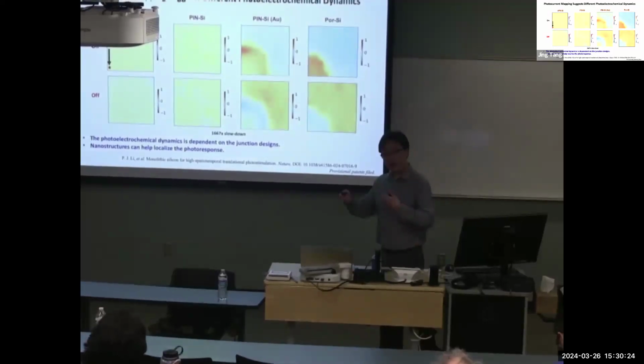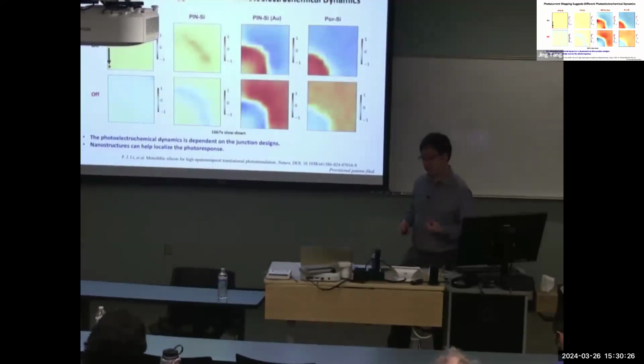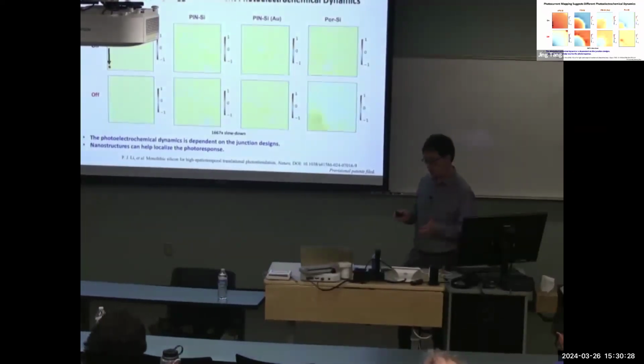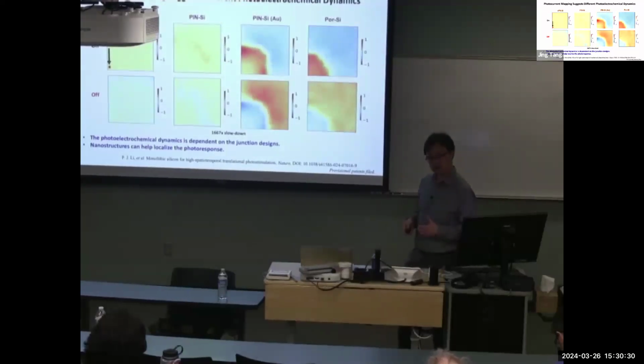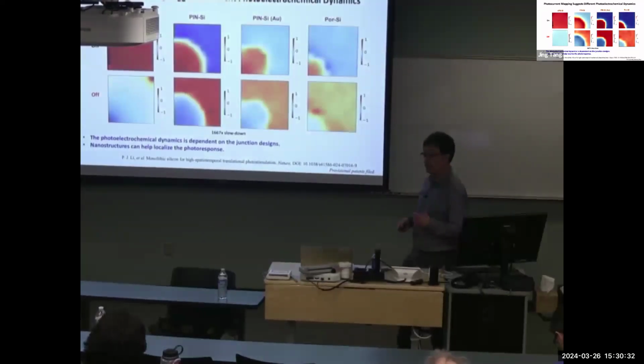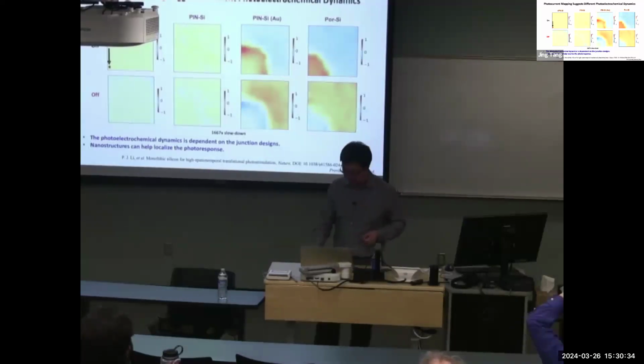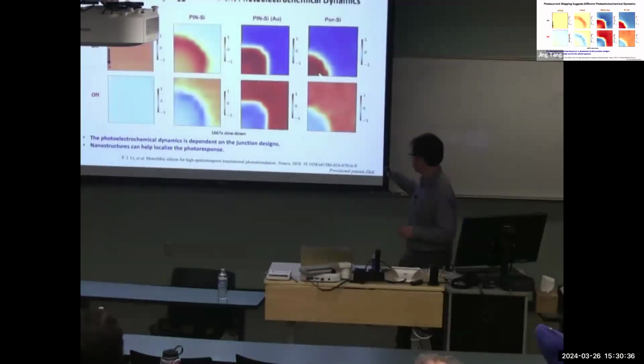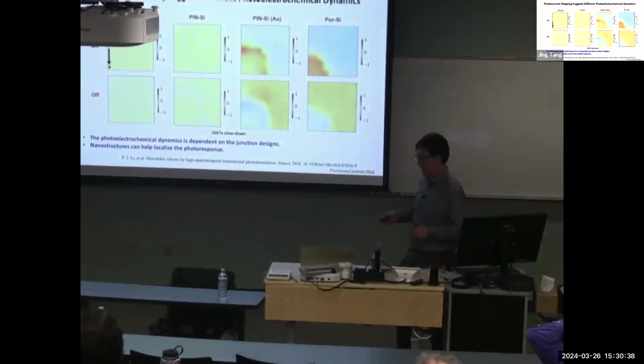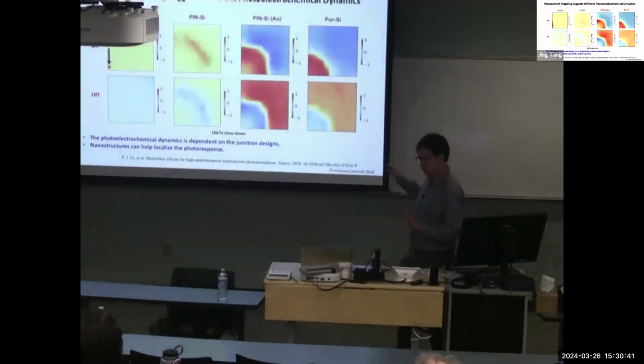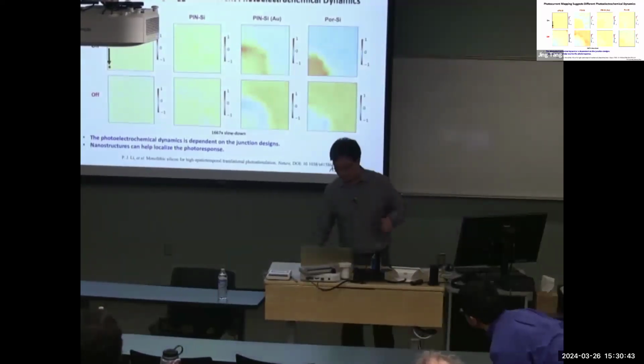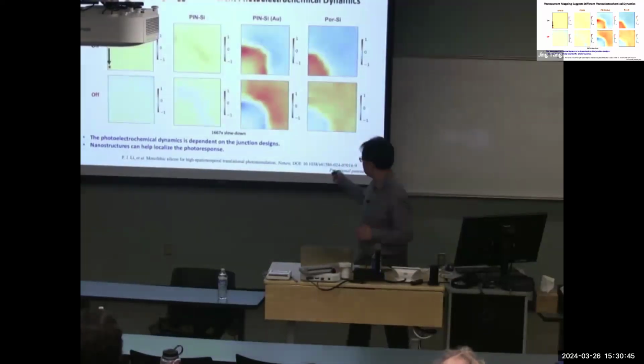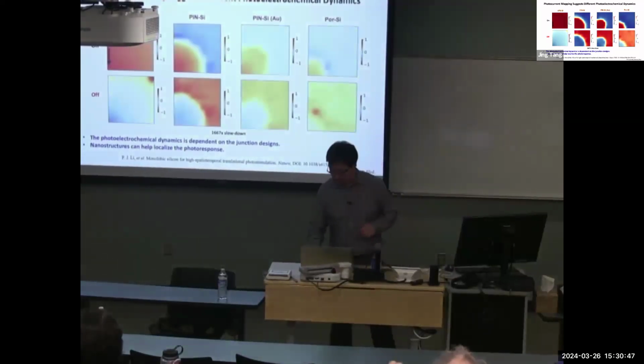This charge balancing is actually important for a lot of biointerface material because you don't want to locally accumulate a lot of toxic species. The charge balance is actually better in terms of biocompatibility. So two messages: one, localization is better, and second, in terms of the charge balancing, you have two polarized domains on the same surface, and the center is only defined by the light spot.